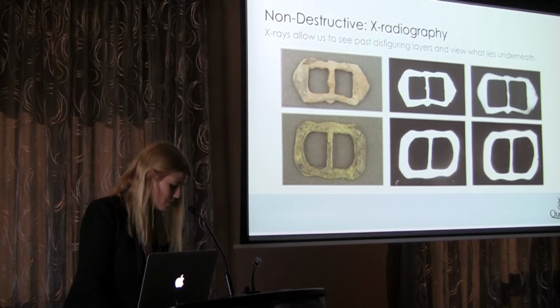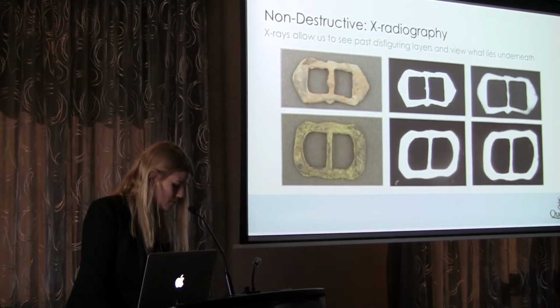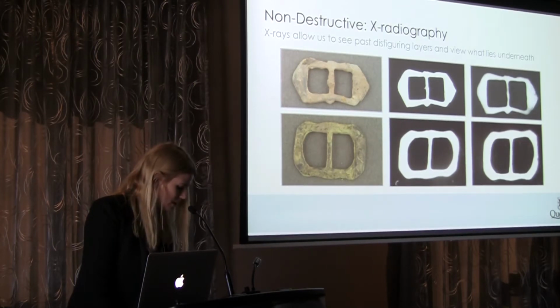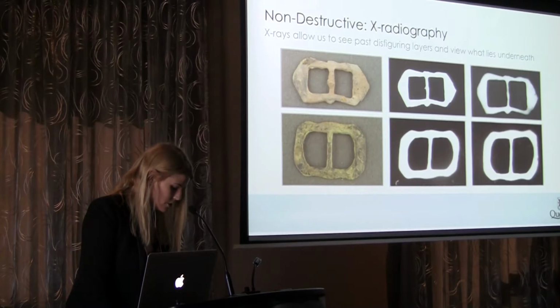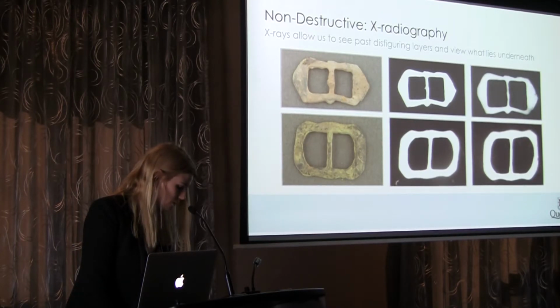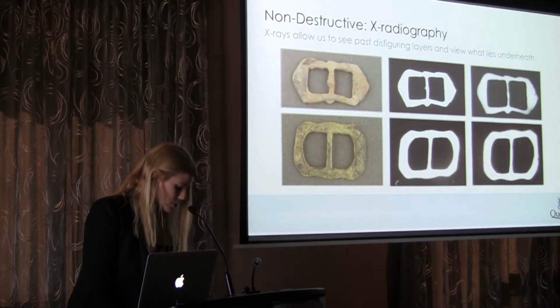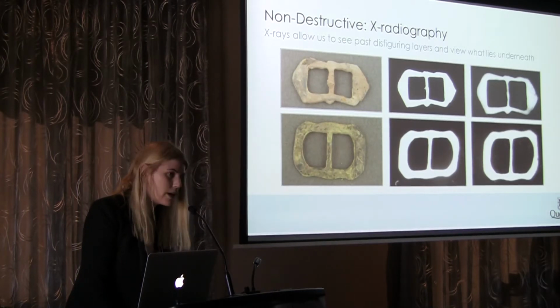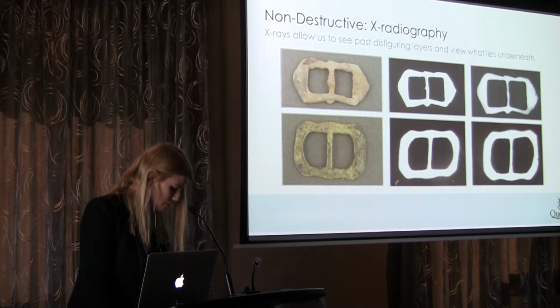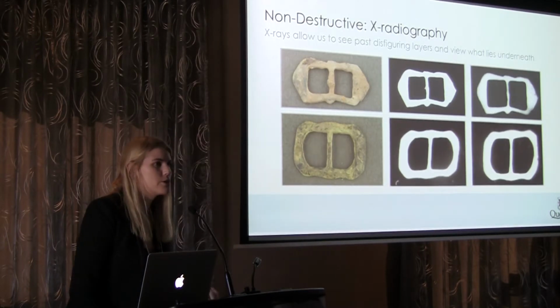After years spent in a burial environment, the original surface of metal objects will become mineralized and no longer resemble metal. In the above radiographs, we hope to determine how much the original surface of the buckles had mineralized. We do not want to scrape away the original surface during treatment, so X-radiography was particularly important during our treatment of the Herstmonceux buckles.